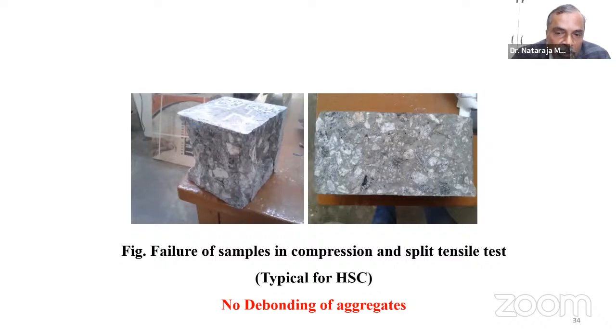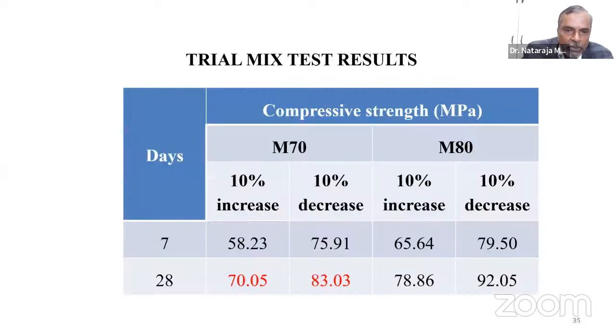Kindly see there is no debonding of the aggregate happening. Means that all aggregates are cutting across. Means that the aggregate has really contributed to the strength. There is no debonding. This is where the importance of the transition zone comes into picture. The transition zone is so strong, it is able to hold the aggregate. It is embracing the aggregate completely. So this is where the importance of high strength concrete comes into picture.